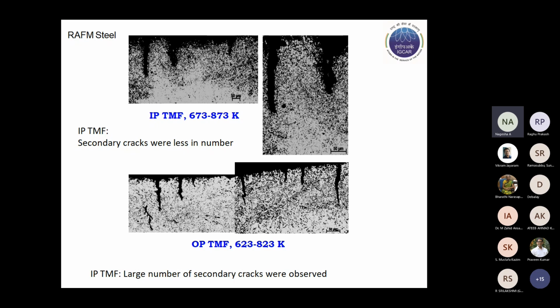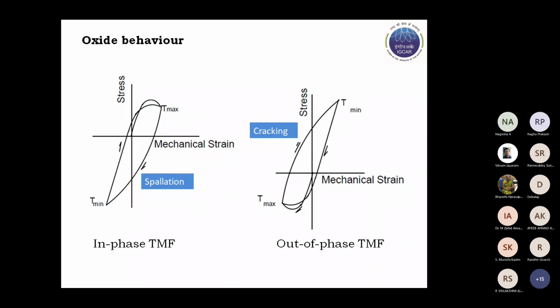Because the combination of maximum temperature and tensile loading blunts the crack to a greater degree compared to what happens in the case of OP TMF, where the peak tensile loads occur with the lower temperature part of the cycle. Typically, in the case of IP TMF, the maximum tensile stress happens at the maximum temperature. Here the oxide forms at the peak tensile load at the maximum temperature. When you reverse the strain, the oxide layer gets spalled off.